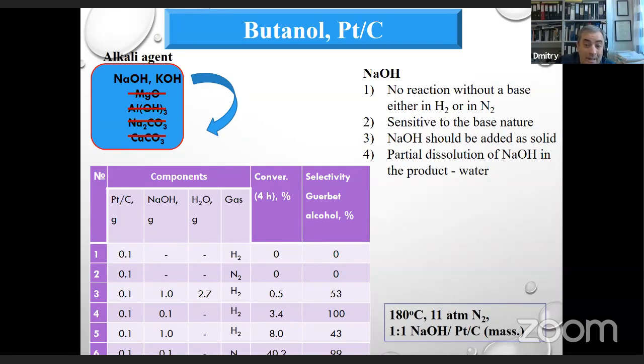First of all, there was no reaction without a base, whatever it was, in hydrogen or nitrogen atmosphere. And then, as I mentioned before, the reaction was quite sensitive to the nature of the base. The experiments were done also in the presence of dissolved sodium hydroxide, but it turned out that conversion is very low, as you can see here. So the conclusion was that sodium hydroxide should be added, at least initially, as a solid. Partial dissolution of sodium hydroxide in the product water is unavoidable, and that's what happened during the reaction. What we see here is that under some conditions, which are listed here, with, for instance, a 1-to-1 ratio between sodium hydroxide and supported platinum at 180 degrees C, it was possible to have rather reasonable conversion with a very high selectivity towards the Guerbet product.